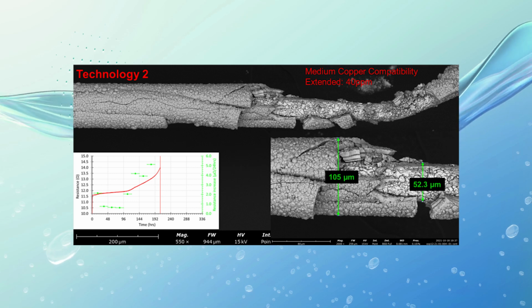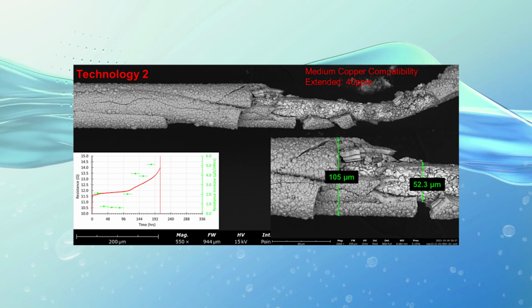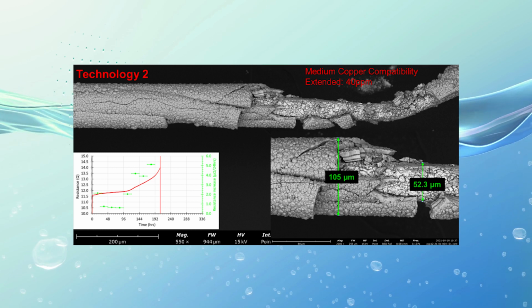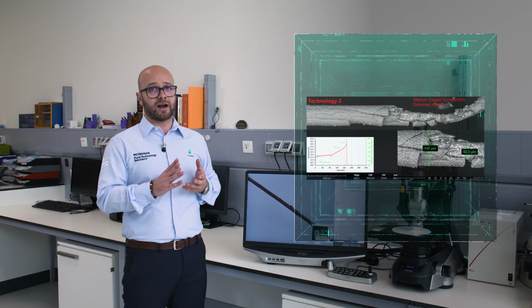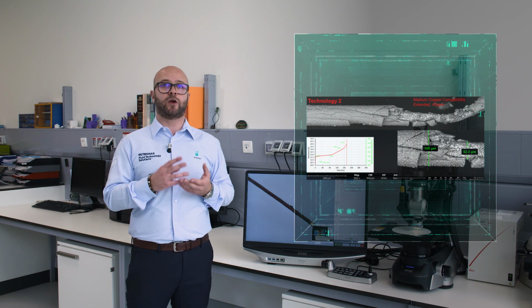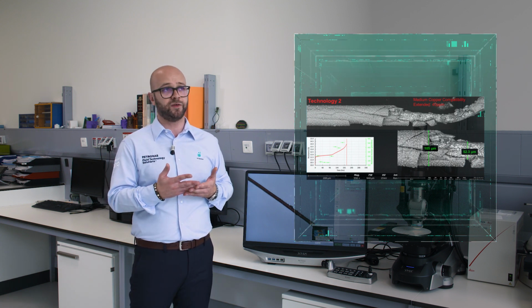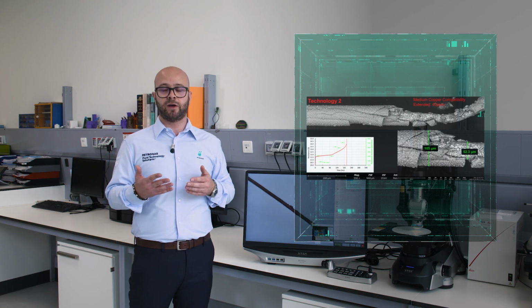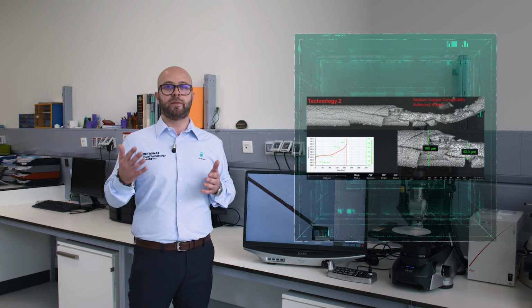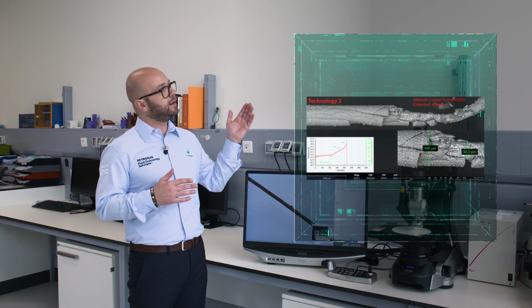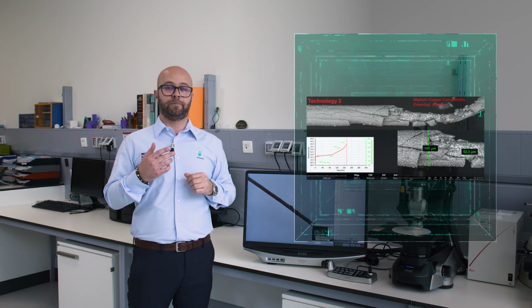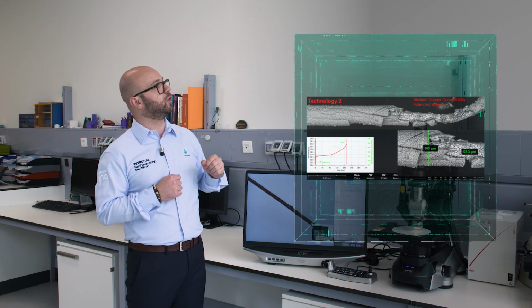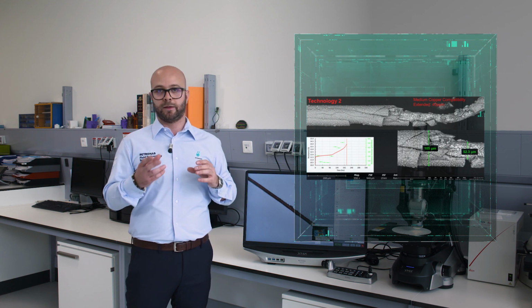Technology 2 is very interesting, the status of the wire after the test, and is characterized by a thick layer of corrosion product that are deposited on the surface, which reach 105 micron. We have always to remember that we start from a wire that is 64 micron thick, and we have the area of pure copper that remain exposed when the coating made up of corrosion product break that is only 50 micron, roughly 50 micron.